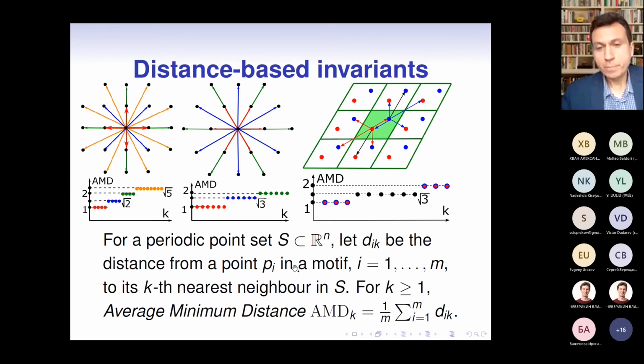To avoid the dependence on any order of points, one way is to take the average over all motif points in a given unit cell. So the last picture shows a less trivial example when we have not a lattice, but a periodic point set with 2 points in this unit cell, a parallelogram. So we take the average over 2 points in this particular case. So when we average, it might seem that we lose some information, indeed. So that's why we have actually a stronger invariant called pointwise distance distribution, which doesn't average over motif points.